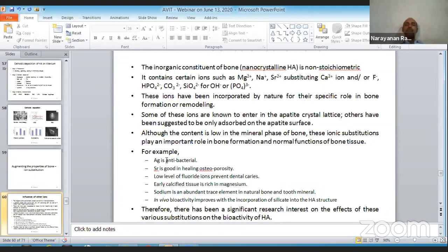And there are many such metals. For example, the bone consists of strontium, magnesium, silicon, silver, and each one has certain properties. Strontium is very good in healing osteoporosis, whereas silver is antibacterial. Even low quantities of sodium are present in natural bone and in tooth mineral. So therefore, there has been significant interest in studying the effects of these various substitutions of HA. The hydroxyapatite, the calcium phosphate, can be added with these ions of magnesium or strontium or silver or bicarbonates, and that coating can help in much better augmentation of the bone implant bonding.